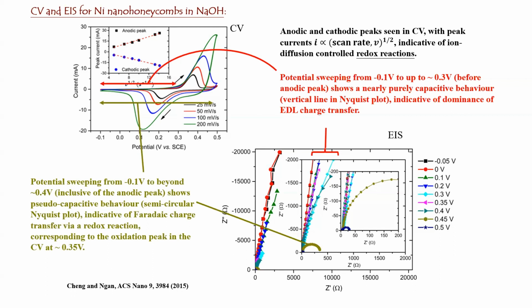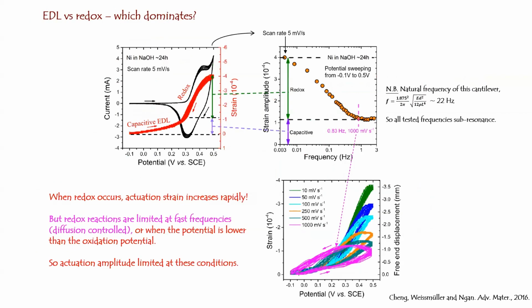But if you now cover the redox, the oxidation and the resistance, the Nyquist plot changes from this vertical line to a semicircle, as I've just said. This means that the oxidation peak will now change the circuit into a parallel arrangement between a capacitor and a resistor. So which one dominates? You have the EDL, you have the redox, both applicable to this nickel or nickel hydroxide system. Which one will dominate?